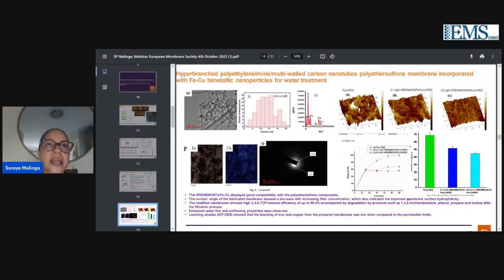Leaching is also a concern when we do nanofillers in membranes. So reviewers will always ask if the material that you've embedded does leach. So in most of our studies, we did some leaching analysis where, when we collected the permeate, we could analyze it for the presence of that particular metal that we embedded. So in this case, we looked at iron and copper. Although we do not have a guideline to compare with, we have South African national standards to look at what are the acceptable levels of iron and copper in water.